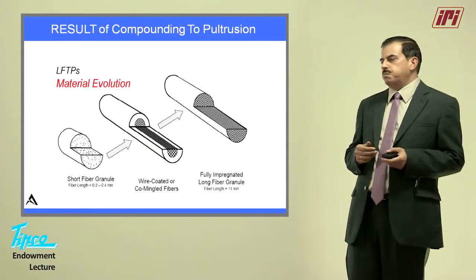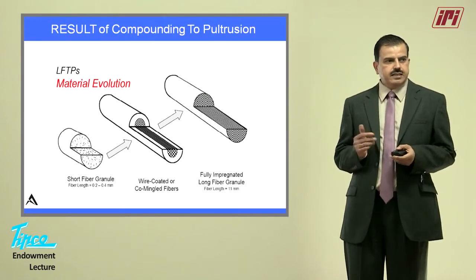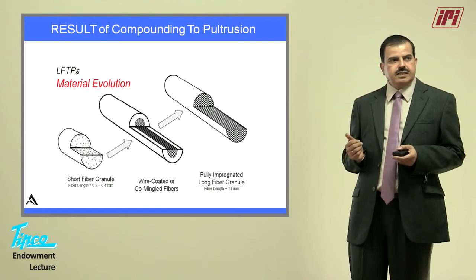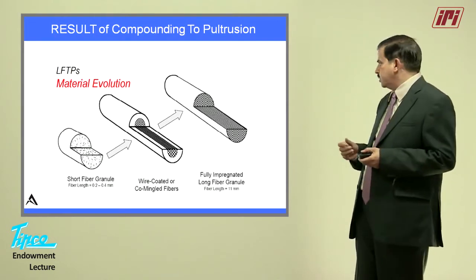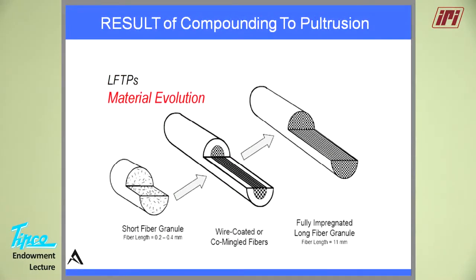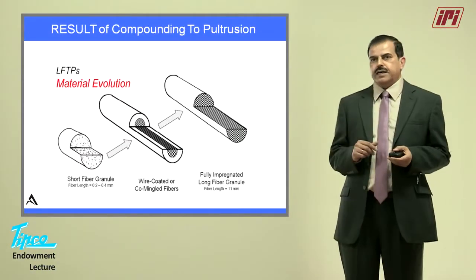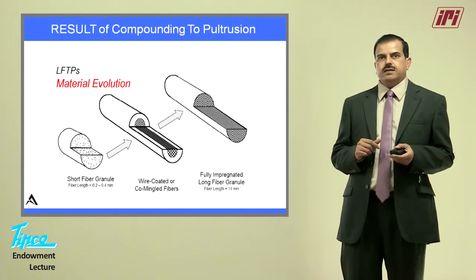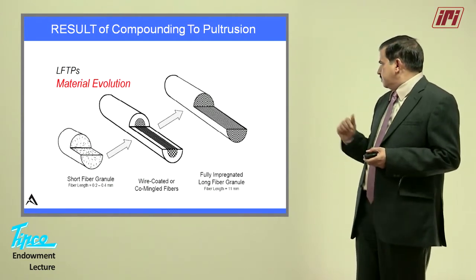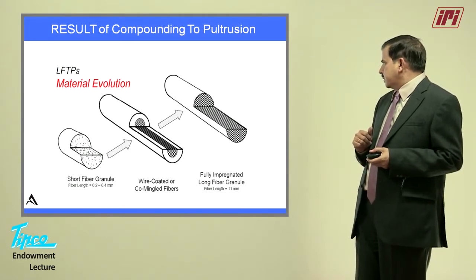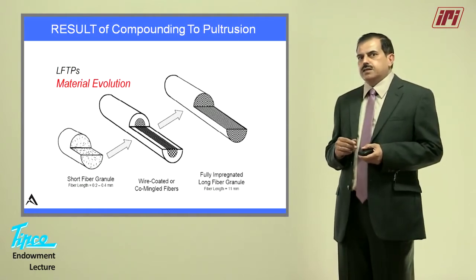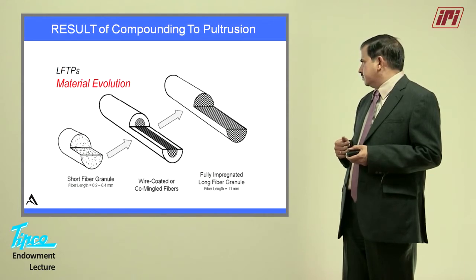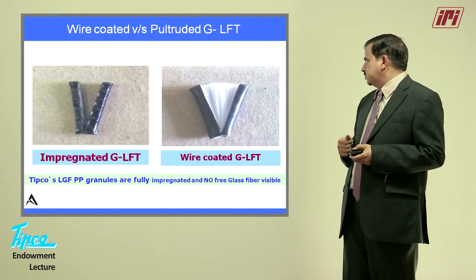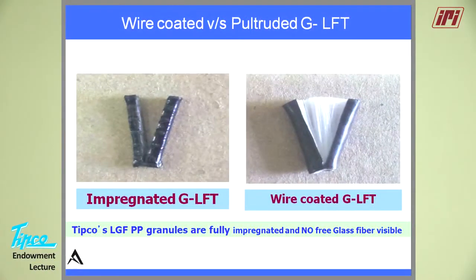The result of moving from compounding to pultrusion, you can see that there is one more step in between which happened. At present I am talking about going from a small short fiber granule to a long fiber granule of 11 mm, but in between there was a time when the long fibers were being made by a process called wire coated technology. That wire coating technology gives you the coating of resins on the fibers, and the result is that if you cut open the granules, you see dry fibers, whereas in the latest technology, pultrusion technology, there is no dry fiber seen.